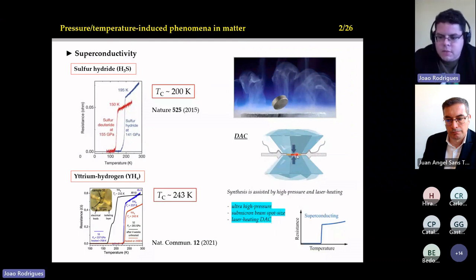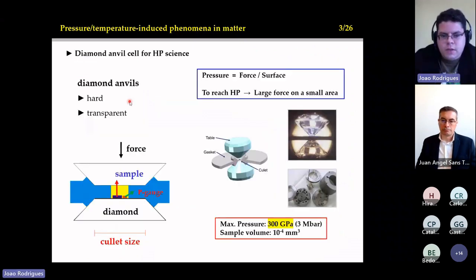It consists basically of two diamonds, and in the middle you can put your sample. Then with the probe, which can be the X-ray beam from the synchrotron or a laser from a Raman system, you can characterize your material. So this is a brief summary of the diamond anvil cell. You know that diamonds are hard and also transparent, and the transparency depends on the properties of the diamond. Okay, and then we mount our sample like this.